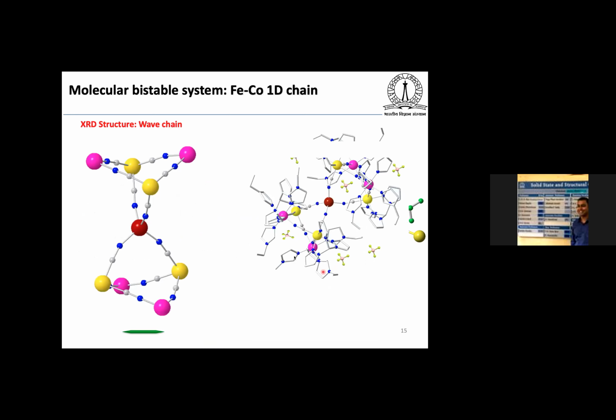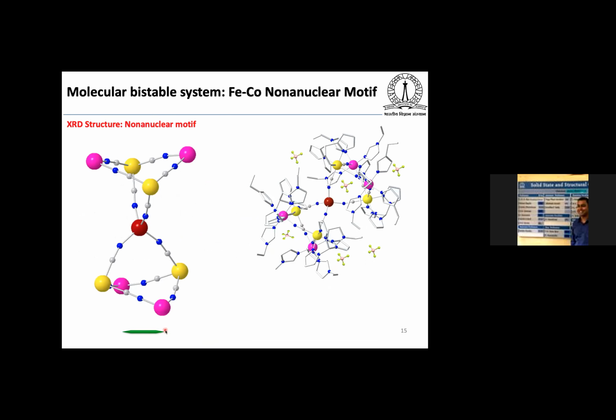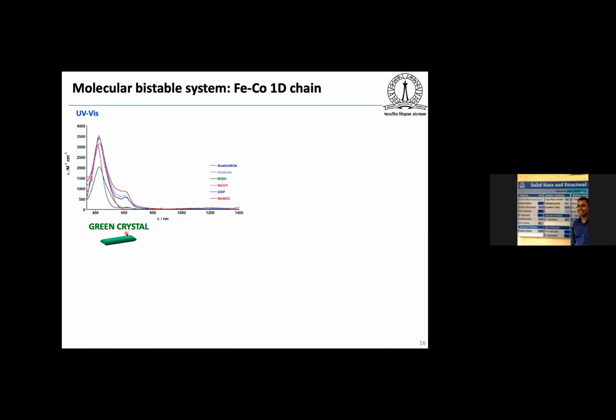And then another interesting thing happens when you get the structure of the needle. We got a very nice nonanuclear motif where you can see the iron that is in yellow in color, and the cobalt 2 that is connected with the ethyl imidazole that is pink color. And you can see in the middle the cobalt is tetrahedral, and this cobalt is always in the cobalt 2 high spin state. I'll show you later the magnetic property.